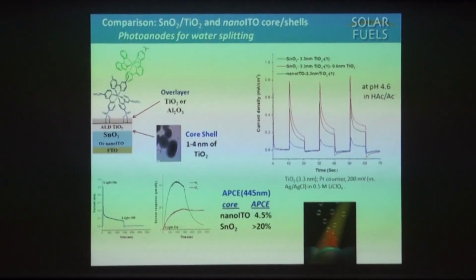But if you keep going and we continue to go, let me just show you the state of the art here at the very end. State of the art here is, all right, keep everything the same. We need this core shell structure. That's great, but there are other things you can do. For example, here's an experiment where instead of the nano-ITO on the inside, we put tin oxide. Then a thin layer of TiO₂.